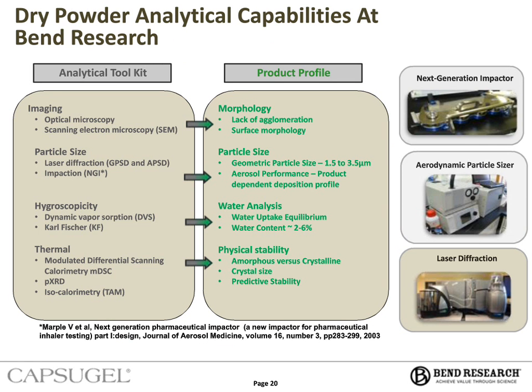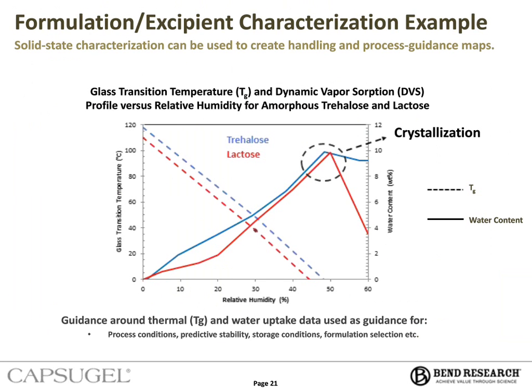on this slide as it's rather busy, but basically what we're looking at here is an amorphous trehalose and lactose formulation. So what we're looking at is the glass transition temperature on the primary y-axis, and then the water uptake on the secondary axis versus relative humidity. So really just looking at how the glass transition temperature and mobility could change as a function of water content. And this kind of thermal and water analysis really can be used as a guidance for process conditions. So what kind of relative humidity should we target in the spray drying process?